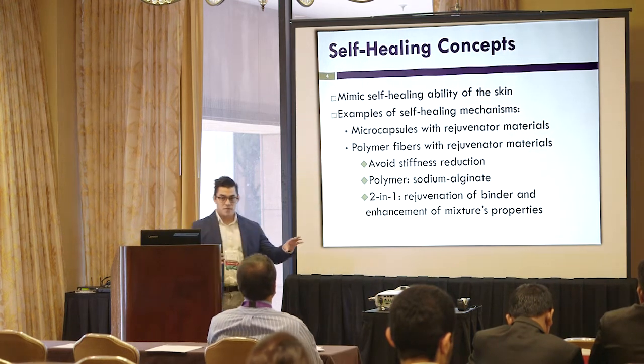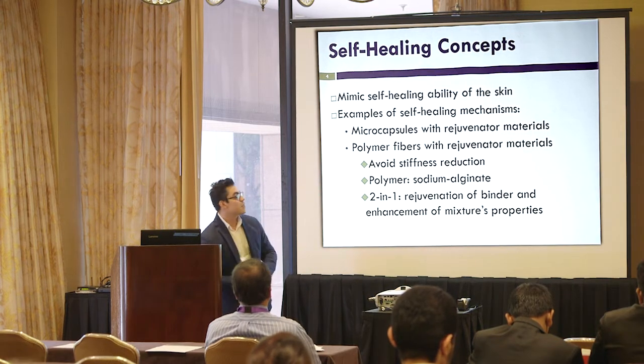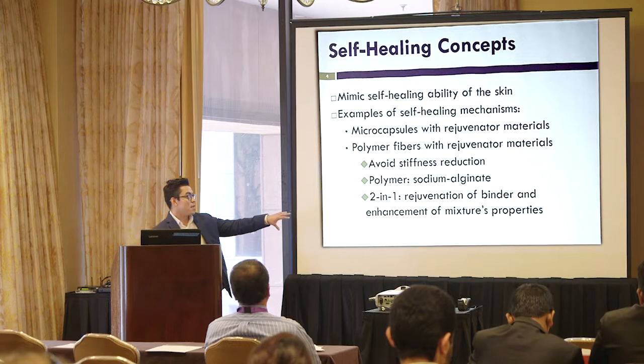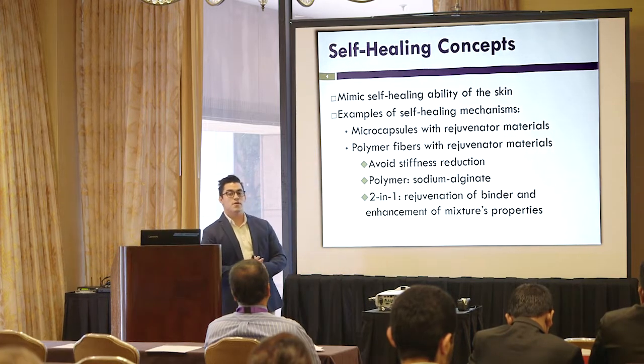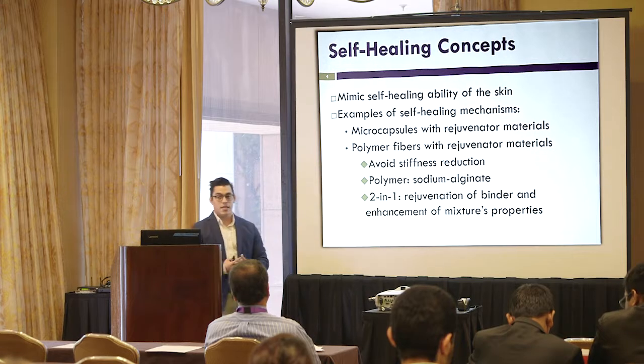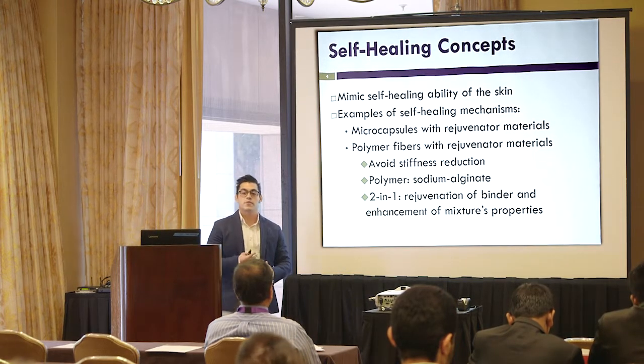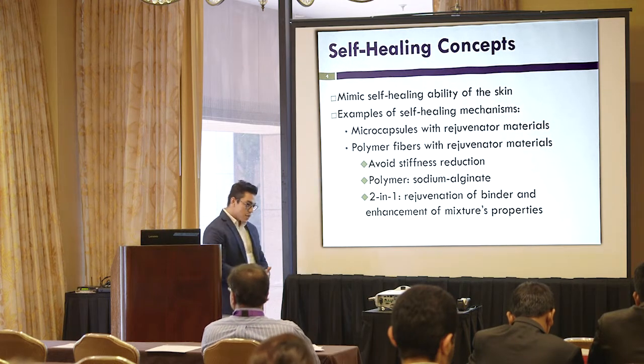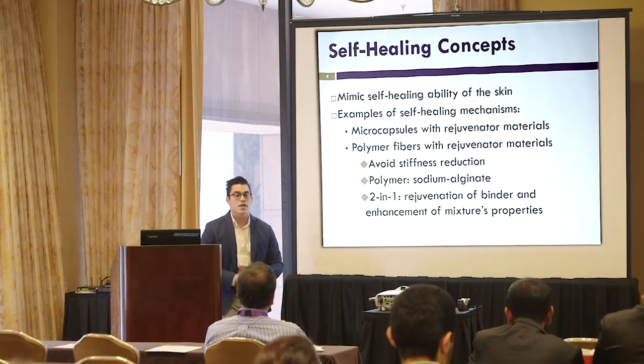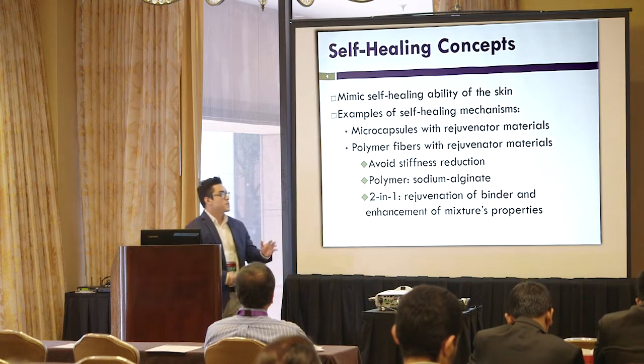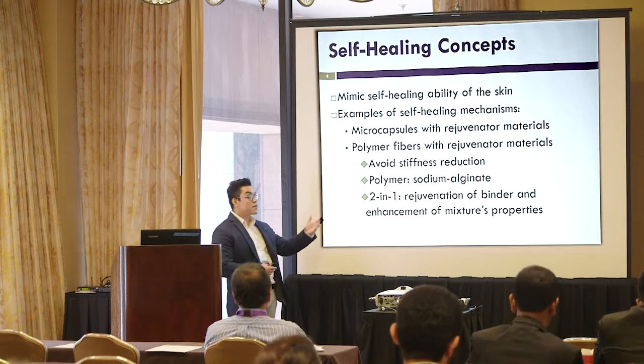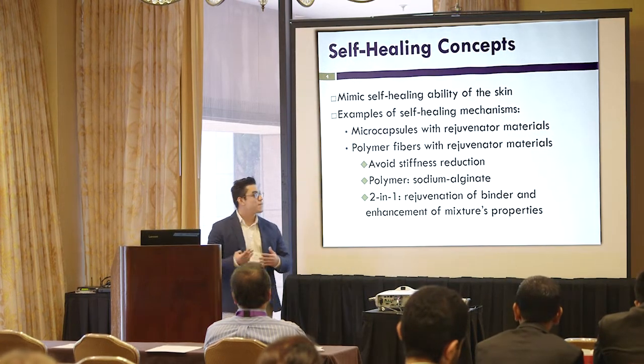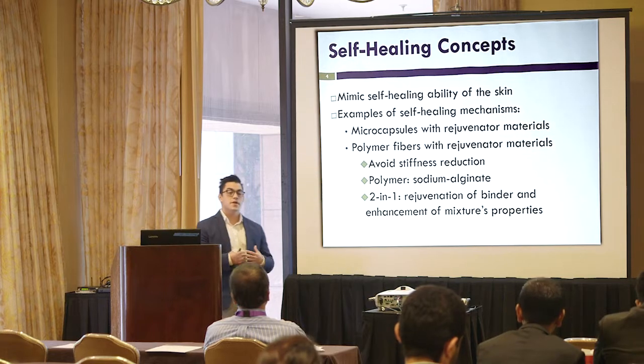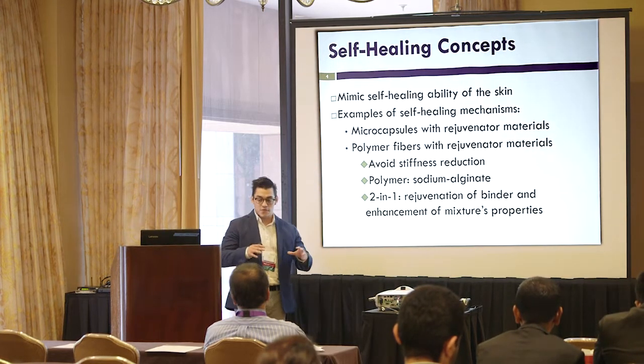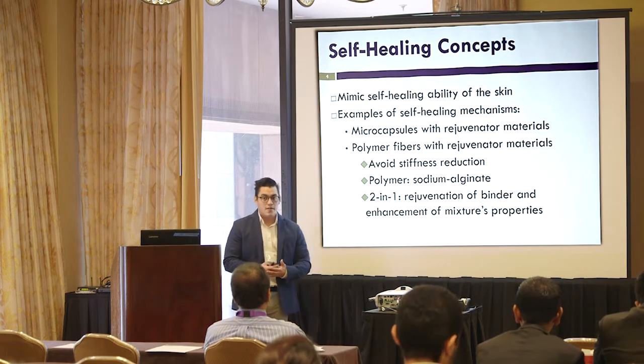We have microcapsules containing a rejuvenator product as a core material, and lastly, we have developed these polymer fibers containing a rejuvenator product. So the idea is to incorporate this type of material whenever we are producing a new HMA mixture, and after some years of service life, when a crack starts to propagate, we're expecting the crack to pass through these microcapsules or fibers, break these fibers or capsules, and release the rejuvenator product. This rejuvenator product is going to help to dissolve the binder around the crack so we can close the crack and hopefully extend the service life of the pavement.